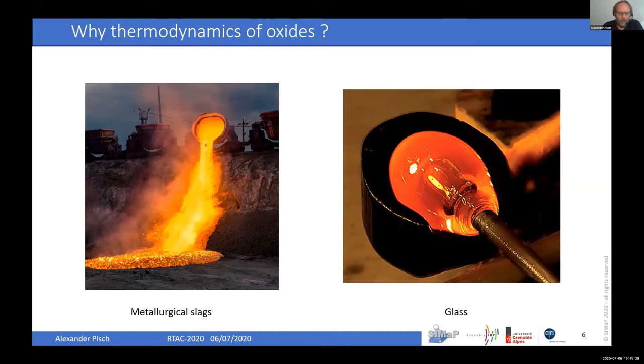And on the right side, glass production. In both cases, the thermodynamic properties are important for the liquid state. So it's multi-component, high temperature. But then at room temperature, when the samples are cooled down, everything is metastable. So we have glasses, an amorphous state. And we also want good quality data for these metastable areas. I will show a little bit later and come back to this point.